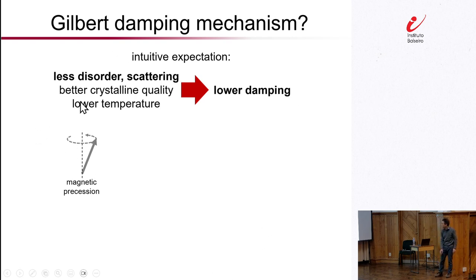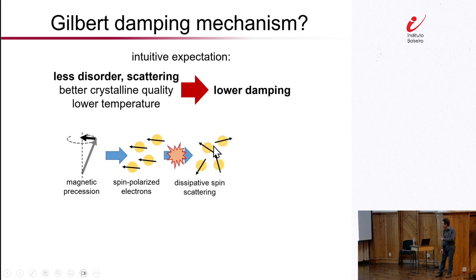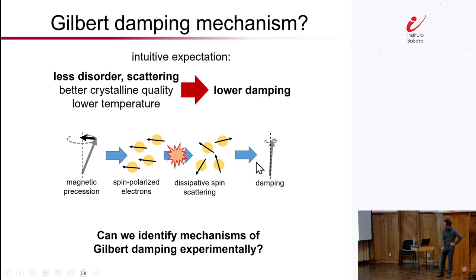So when the magnetization is precessing, what you're actually doing is generating a transverse magnetization component, which at the end of the day consists of a bunch of electrons with a particular spin polarization. Right? Now, if there's quite a bit of electron scattering in the material, there's also a greater chance that the spin polarization would also be scattered, would be randomized. So you would expect that in the presence of a lot of scattering, you would also have spin scattering, which then results in a smaller amount of transverse magnetization component. So you would end up with a higher amount of damping. Okay. So this picture is, I think, something that a lot of us in the field would intuitively expect.